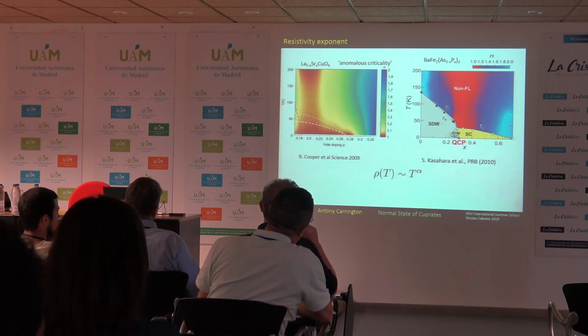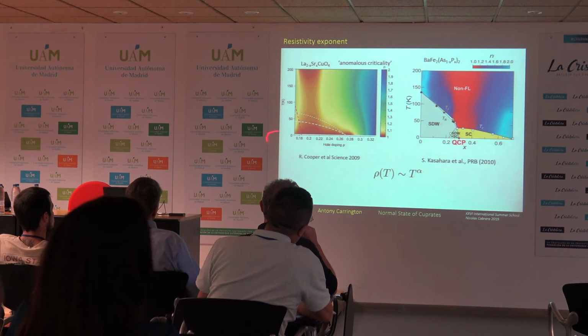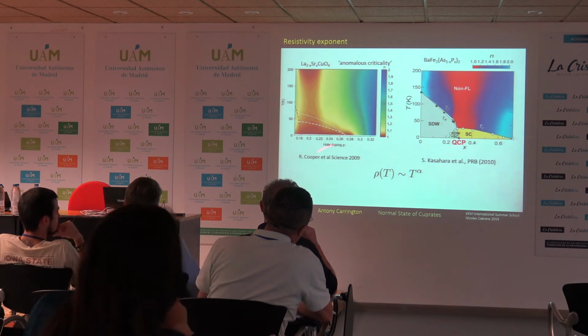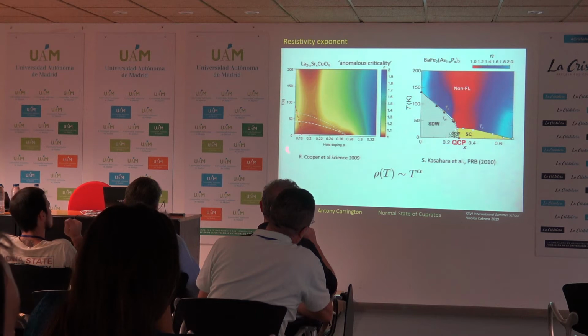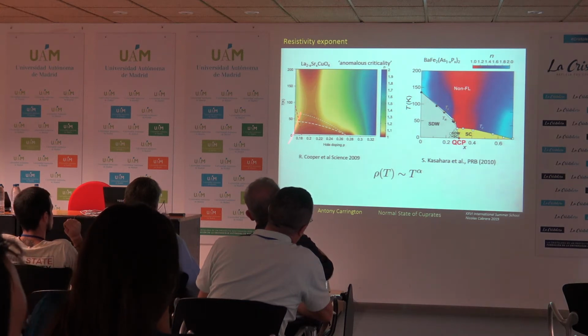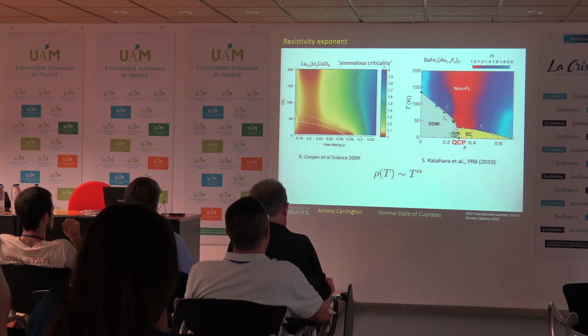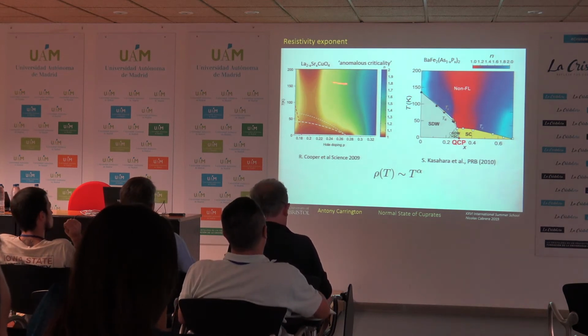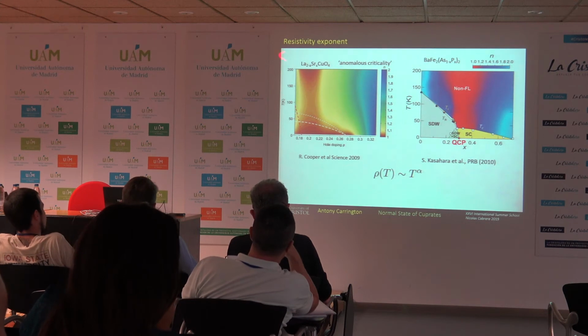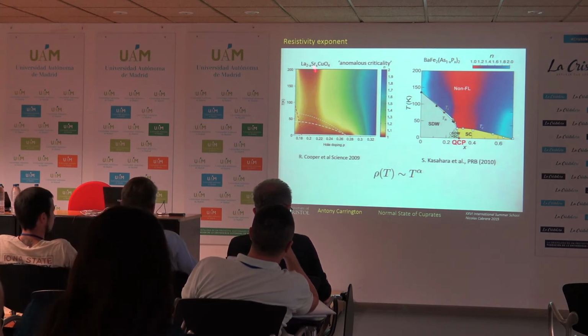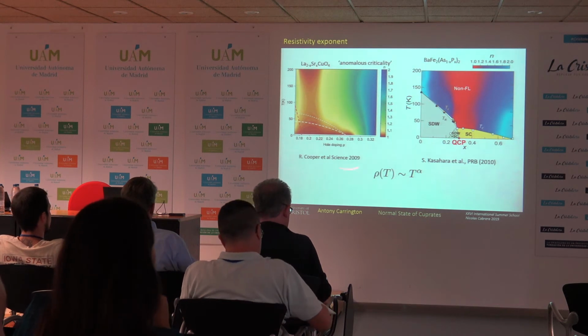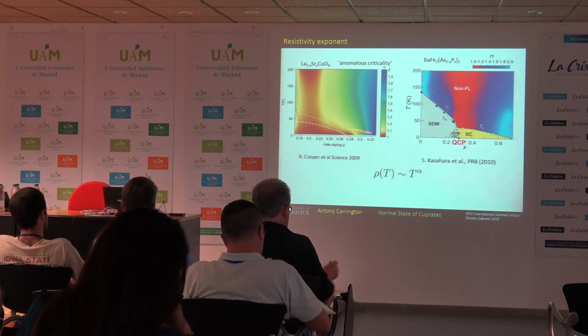how should you interpret that data? Well, it's been remarked many times that near a quantum critical point, you might expect there to be a fan of non-Fermi liquid behaviour where the resistivity varies linearly with temperature. So this is what this looks like in the cuprate. This is some data from my colleague Nigel Hussey on lanthanum strontium copper oxides, which can be doped over a large range.